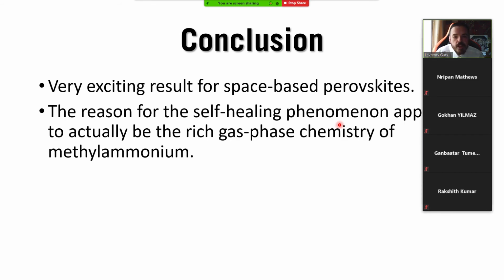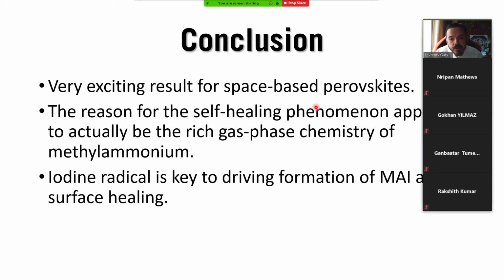The reason we have self-healing is because we have rich gas phase chemistry involving methylammonium and iodine, and the iodine radical is key to driving the reformation of methylammonium iodide and healing the surface back up.